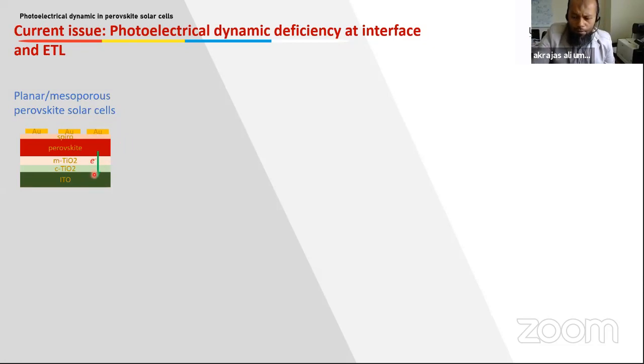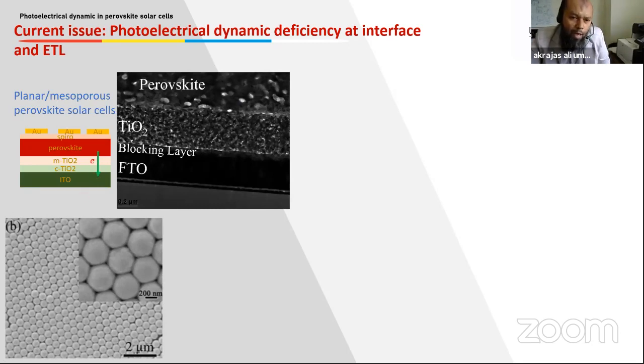This is a typical structure of the perovskite solar cell, where we have a compact layer of TiO2 on top of ITO or FTO. Compact TiO2 can be a compact layer of colloidal particles of TiO2 or a thin film of TiO2. And then on top of this compact layer, we can see a mesoporous layer of TiO2. We can imagine how the properties of the porous structure, which contains large pores and also dead pore structure, are detrimental to the photoelectrical dynamics in the devices.